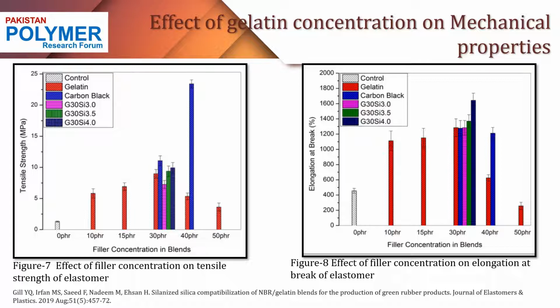But on increasing the gelatin concentration or pHr from 30 to 50 pHr, the tensile strength goes on decreasing. This behavior might be because of the increase in filler bonding or filler agglomerates formation that reduce the transference of load from matrix to the filler. This reduces the tensile strength as it makes the elastomer more brittle and reduces the strength of the elastomer.